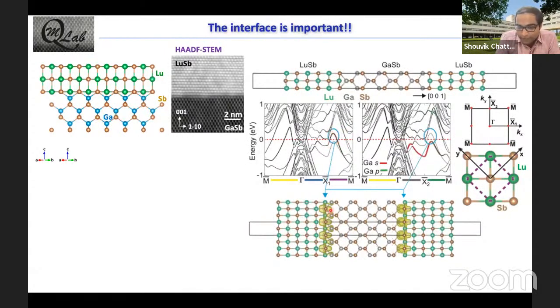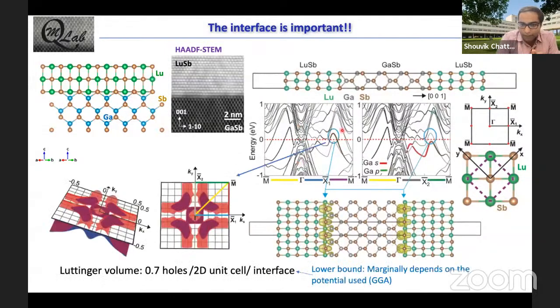And if you look at the charge density distribution, you find that although they are very well distributed in plane, they're very tightly confined in the out of plane direction. So we can also get some quantitative numbers by looking at the Fermi surface corresponding to these interfacial states. And when we calculate the Luttinger volume, it comes out to be about 0.7 holes per 2D unit cell